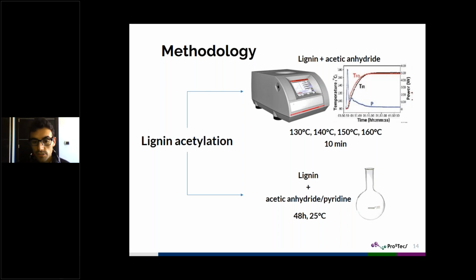You can see in literature a lot of different times and temperatures, but generally what we want is to try to give the time enough to get the most acetylated lignin possible by this pathway. On the other hand, we have tried another completely different lignin acetylation, that is by the use of microwave power. With the use of microwave power, what we can do also is eliminate pyridine, that is a very harmful solvent. So just by means of lignin and acetic anhydride, we can obtain acetylated lignin.